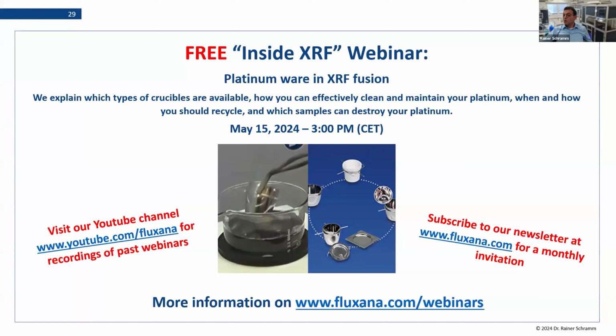Another question, how to get specific analysis, especially sample with high concentration of SiO2. So I understand it in a way how to fuse pure quartz or high SiO2. You have to make sure that you have enough heat, because quartz needs heat, needs power, yeah? Because we know that quartz glass also has a high melting temperature, so you have to make sure that you grind your sample fine enough, that you dilute it good with flux, and that you have a fusion system with high temperature and a good agitation.